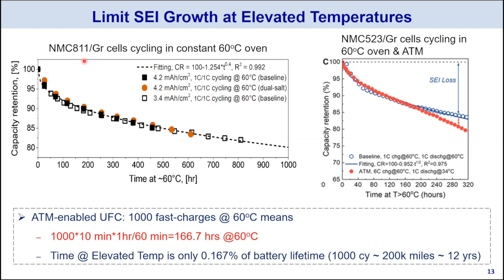The figure on the left is for NMC811 graphite cells. We put them in a constant 60 degrees Celsius oven and cycle all of them, so that we know the SEI layer induced degradation at elevated temperature. Those are for very thick electrodes, 4.2 milliamp hour per square centimeter loading, 1C cycling, or medium 3.4 loading, but with the same active material, same BET area, and therefore their SEI layer characteristics remain the same. Also, we deal with different electrolytes. And as you can see, all the data collapse onto one single curve between the capacity retention and the time, and as a matter of fact, following nearly square root of time, as we would expect. So at this point, you can see that it's all about time.